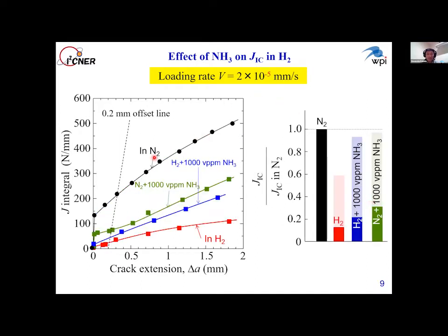Next, I'd like to show you the result with lower loading rate. The curves in the graph, except for the curve of nitrogen, changed. Regarding the fracture toughness value in hydrogen, the reduction was more significant. We can find a similar trend in other hydrogen embrittlement experiments. The reason why the effect of hydrogen is more pronounced with a decrease in the loading rate is that more time for hydrogen uptake and hydrogen diffusion is provided by the reduced loading rate. Regarding the mitigation of hydrogen embrittlement by ammonia, the effect was greatly reduced.